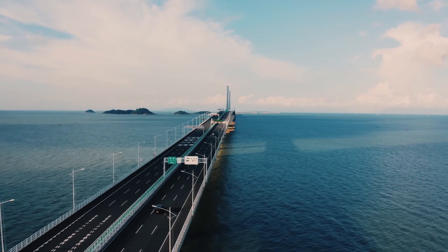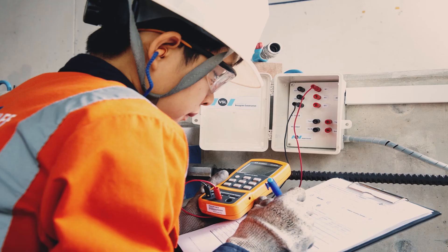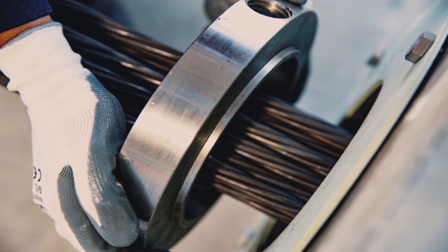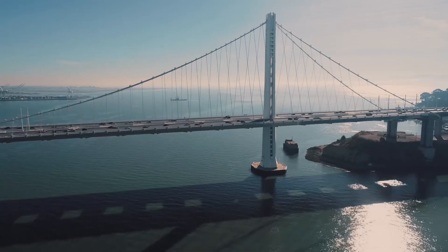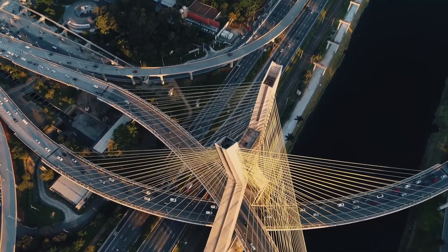The best strategy overall to minimize life cycle costs is to select durable PT systems from the start, ensure they are properly installed, check and document their final installed quality, and properly maintain the structures. The collapse of the Ynys-y-Gwas bridge in 1985 led to industry-wide action: FIB and specialists like VSL initiated R&D into grout mix design and correct grouting procedures. The inclined tube and wick-induced tests proposed by VSL and FIB were adopted in the Eurocode in 2007, and FIB's 2005 protection level concept is integrated into the ongoing revision of Eurocode EN 1992. Even in the 2020s, durability of post-tensioning tendons remains a challenge, but it is achievable if state-of-the-art procedures and testing are made mandatory and consistently implemented by trained, certified crews alongside long-term regular maintenance.